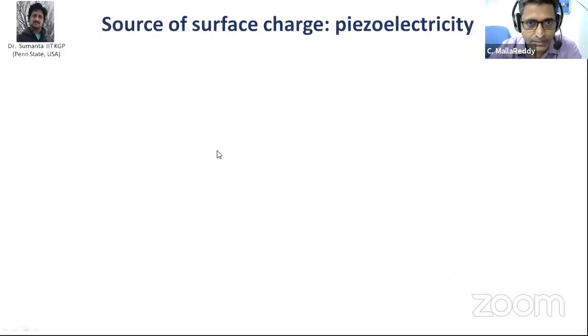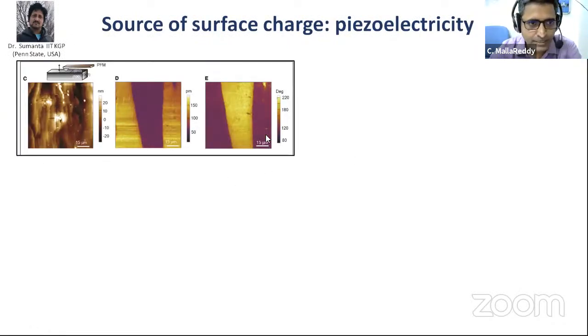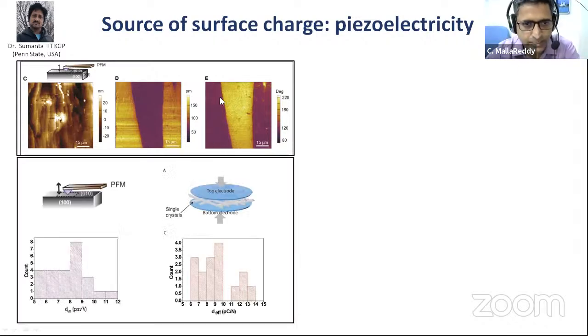Since it is a piezoelectric material, we wanted to study it with the PFM instrument. Basically what you do here is apply a voltage bias, an electrical bias, and since it is a piezoelectric material, there will be a mechanical change. The material either would go down or it would bulge out. Locally, that gives you an estimation of the piezoelectric response of the material. We have done this, and we understood that this is a good piezoelectric material. For organic materials, this is not really great, but it is also not very bad. This is a moderately good piezoelectric material.